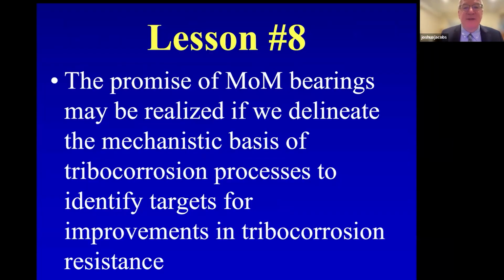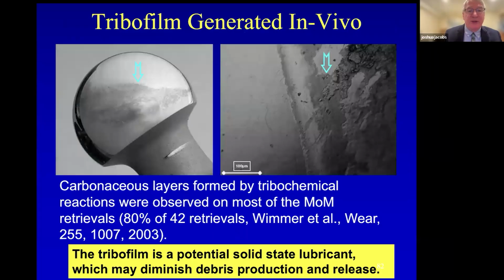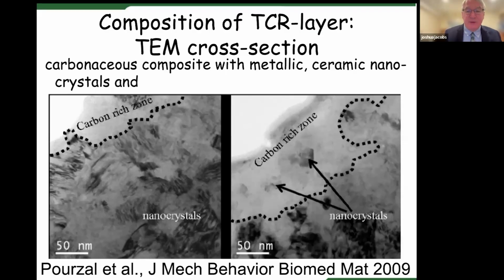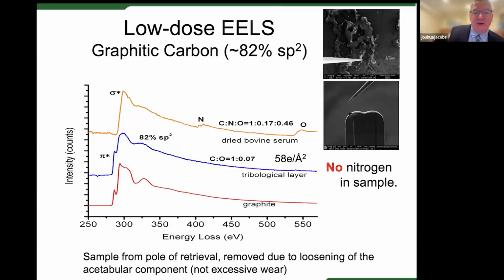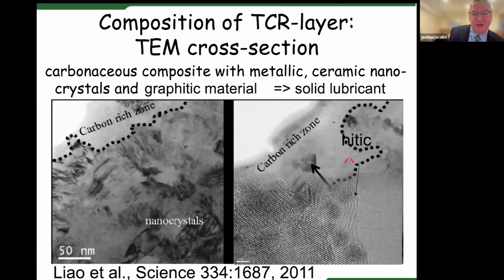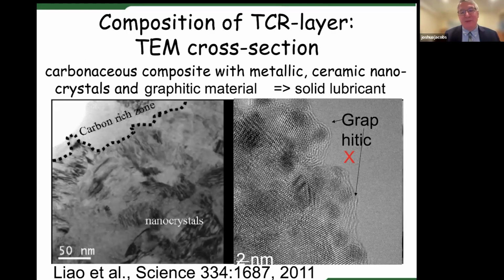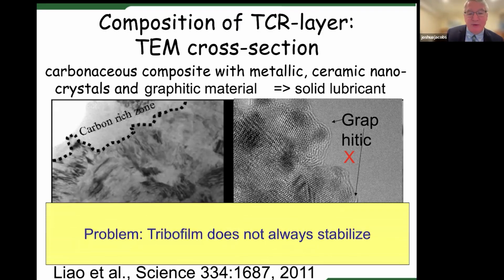And the second to last note, and this is for the material scientists here, is that we can probably do better in this area if we understand the mechanistic basis of why our implants are corroding. We found on some retrieval studies that a tribochemical reaction layer is present on some of the successful devices. And in fact, if this could be stabilized, it can serve as a solid state lubricant. So pursuing this with some colleagues at Northwestern, Laurie Marks, using TEM techniques, we found this carbon-rich zone turns out to have this pi peak, which means that there's a graphitic solid-state lubricant that can be associated perhaps with decreasing this amount of metal release from this tribocorrosion reaction.